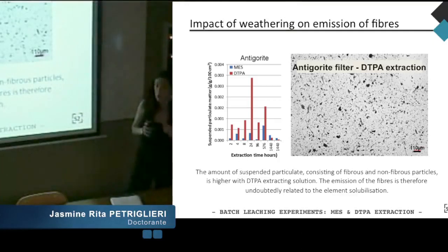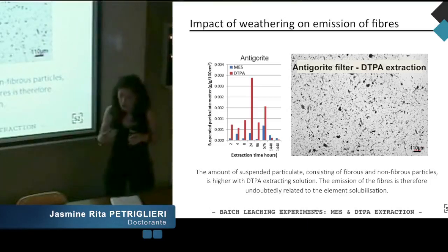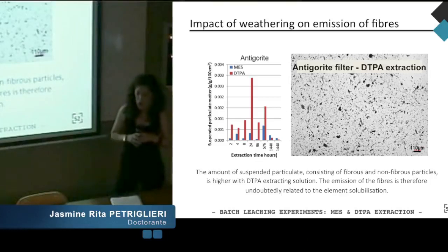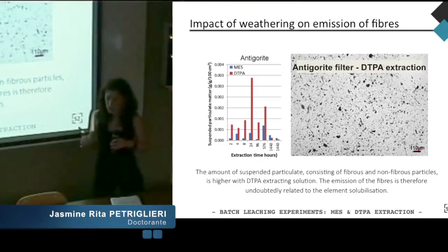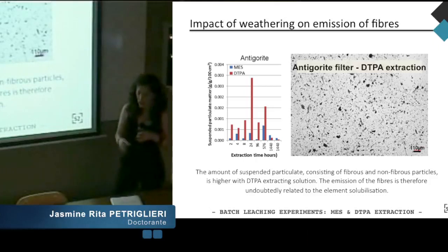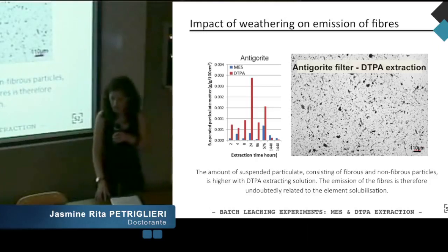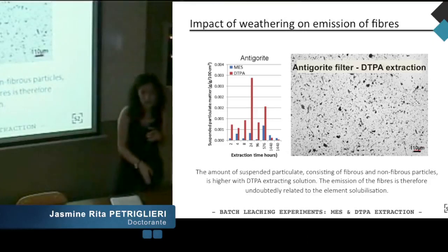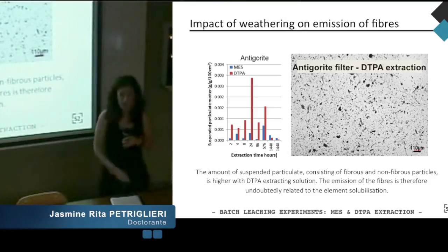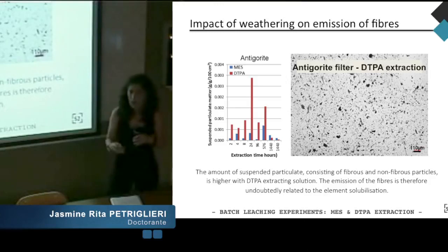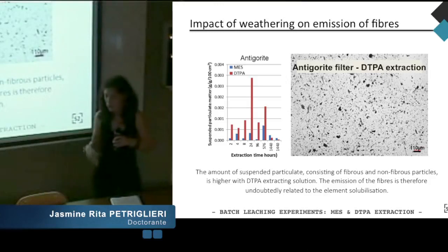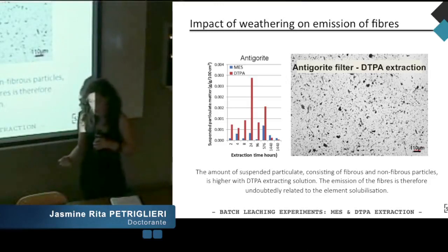It's not surprising, but extraction realized with DTPA is more important and stronger than extraction realized with MES. And this generates a greater amount of suspended particulates in the solution. The emission of fibers is therefore undoubtedly related to the chemical alteration of this sample. Chemical alteration induces and participates in the processes of generation and release of fibers into the environment.